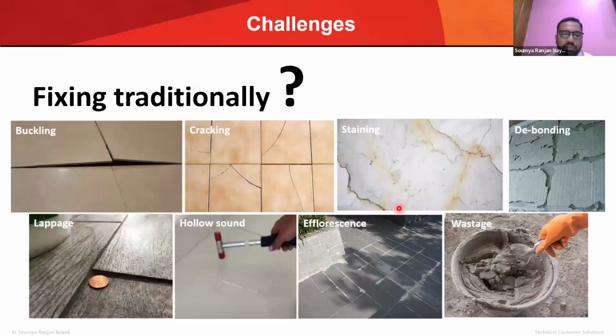When you use only cement for tile fixing, you will not be able to cure it, because you apply the tile or stone on the cement. Due to lower strength and shrinkage, buckling happens, and due to shrinkage and cracks in the cement layer, cracks eventually develop in the tiles. Due to gaps and hollowness in the binding material, like tile adhesives, dirt enters into the gaps and into the white marbles and tiles. Then obviously if the cement does not achieve its desired strength, our tiles and marbles will debond, and we don't have control over shrinkage.